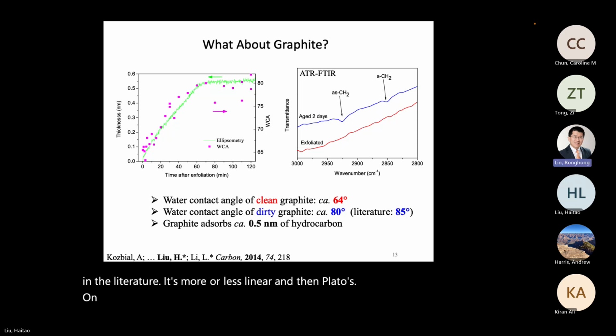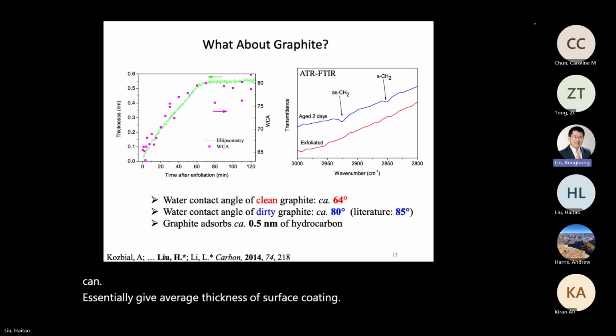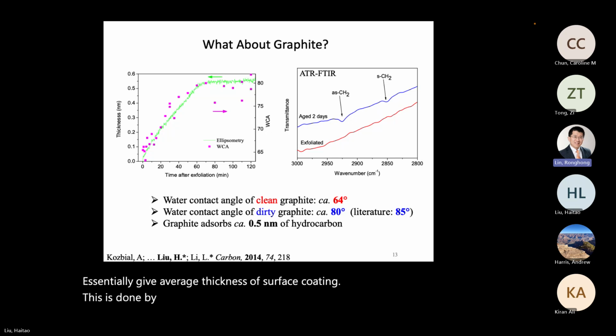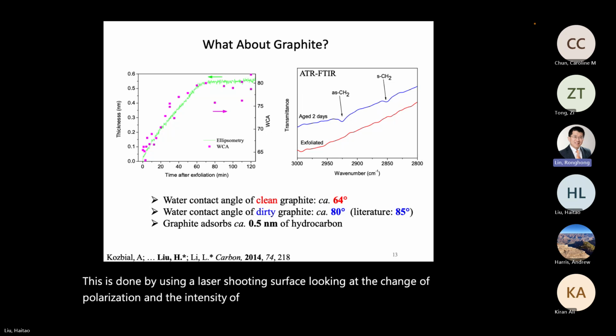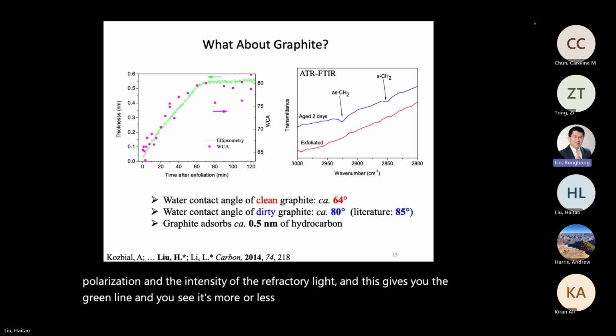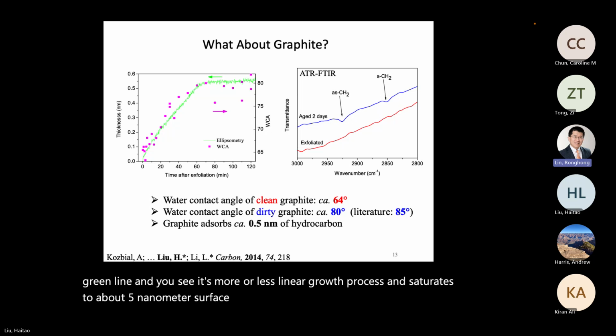On the same sample, we can also do ellipsometry, and this measurement can essentially give an average thickness of surface coating. This is done by using a laser, shooting the surface, looking at the change of polarization and the intensity of the reflected light. And this gives you the growth line, and you see it's a more or less linear growth process, and it saturates to about 0.5 nanometer surface coating.